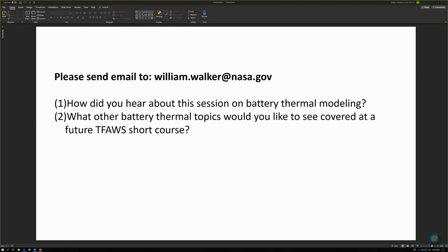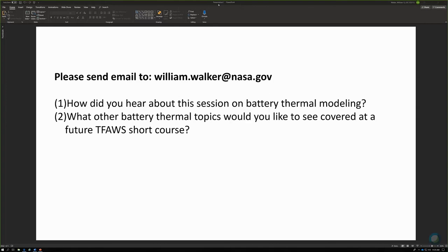And then from there, you could start making approximations on, you know, intuitively that a chunk of that energy is going to be ejected away. And so you could do a parametric, or potentially Monte Carlo style parametric, where you evaluate, for your given battery pack, how much of that heat has to be ejected away for you to meet your success criteria. Or you could look at it the other way around, but that would be my approach with lack of test data to back it up. Hope that answers your question.